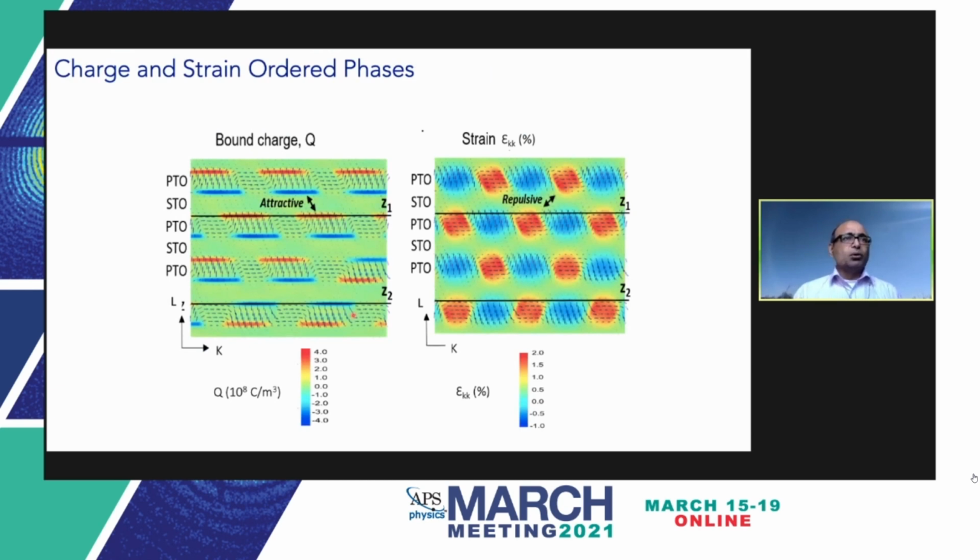When you look at some more microscopic details, some interesting things happen. It looks like there's a charge ordered state. So there are polarizations locally that are up and down and left and right, and there are bound charges that are charge ordering. And if you actually calculate how much of this charge is there, it is approximately the amount of charge being pumped by the light. So there's a nice sort of intuition there that we're dumping charges, and this material finds this state in order to tuck it away and become an insulator again.